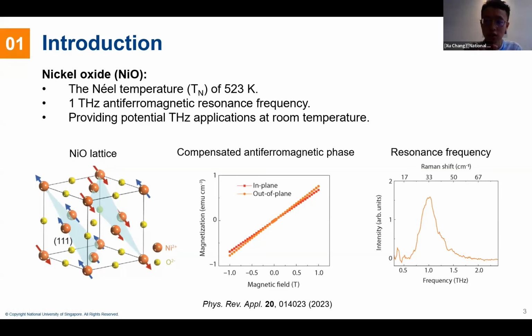Because our single crystal is 1 millimeter thin, if we inject a DC current, it will soon come to a uniform temperature. So the nickel oxide lattice is actually heated. The terahertz transmission at that point should behave as an antiferromagnet, because it is not determined by the interface. It is actually caused by the bulk, the antiferromagnetically coupled bulk. I'm not sure whether I've answered your question.